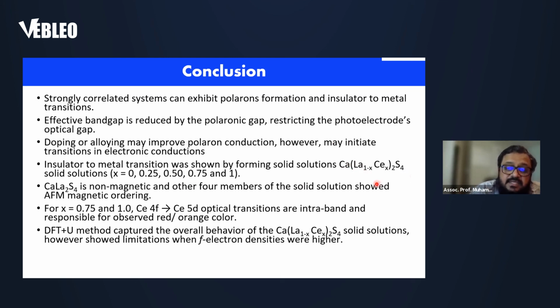The calcium lanthanum sulfide with no 4f electron was non-magnetic. However, the others are AFM. The optical transition, which was the initial goal of the work, I didn't show here because it doesn't exactly go with the title of this presentation. We found that those orange and red colors come due to intra-band transition from cerium 4f to cerium 5d electronic excitation.